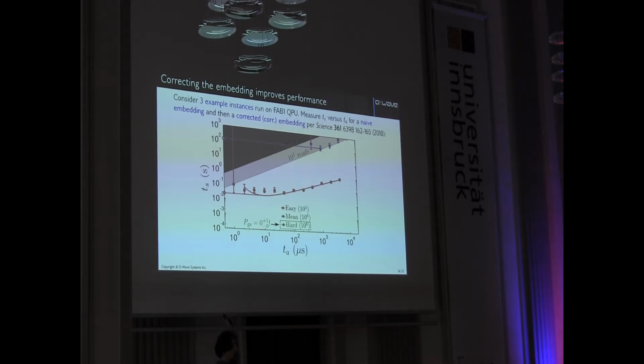That's my Bermuda Triangle, statistical noise. So what I had to do to actually see the results from that mean instance was crank up the number of reads to 10 to the 6, which is that darker gray triangle you see up there. And then I could actually see those results from the mean instance and pull a minimum anneal time. Whereas that hard instance, I did up to 10 to the 6 reads for every anneal time. Nothing showed up. There were no solutions there.